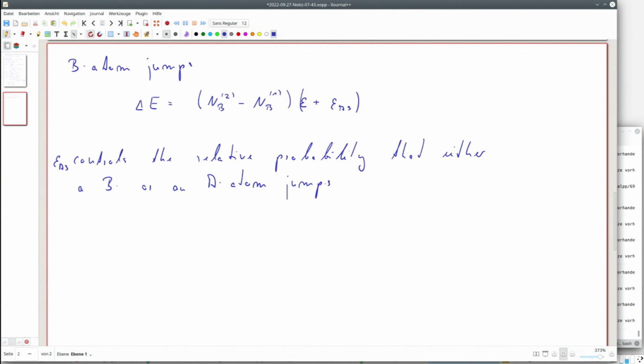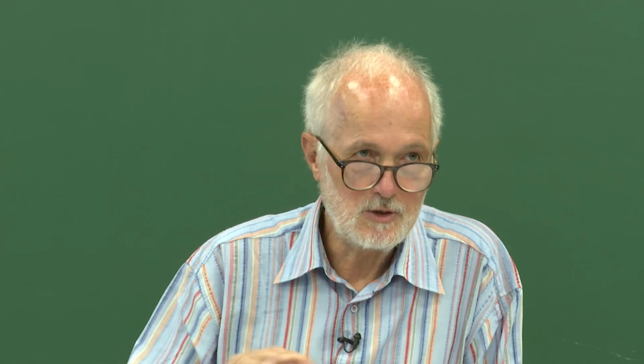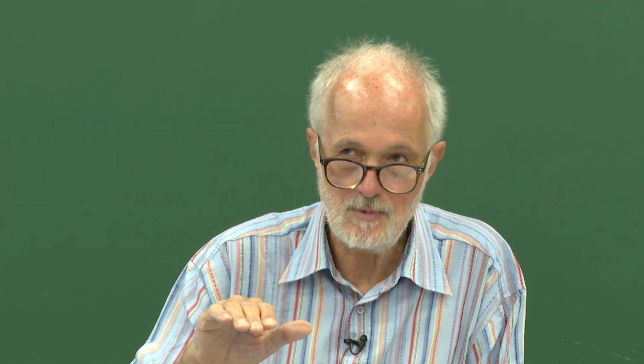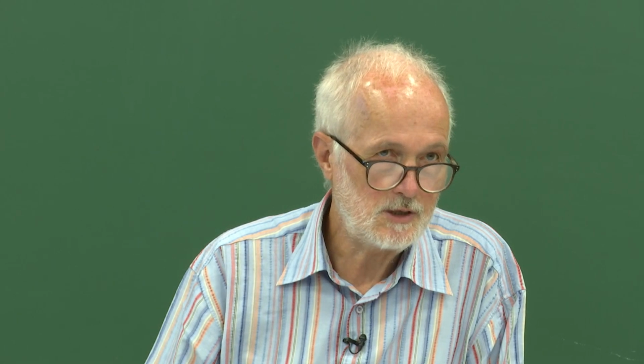And this means, in more experimentalist terms, it's the mobility of the A or the B atoms or the relative diffusion coefficients. And you probably know that diffusion coefficients in a binary alloy of two species are not necessarily the same. Often you have huge differences in mobility between two species, which can lead to strange effects sometimes. This I wanted to show here.